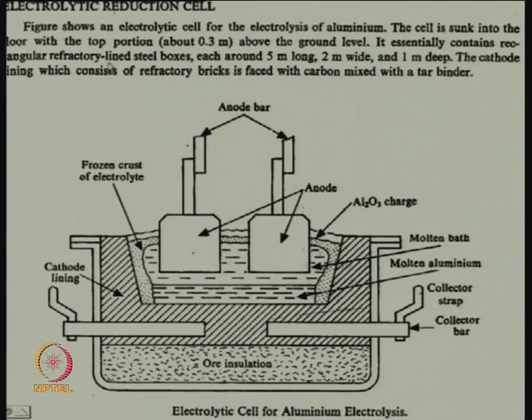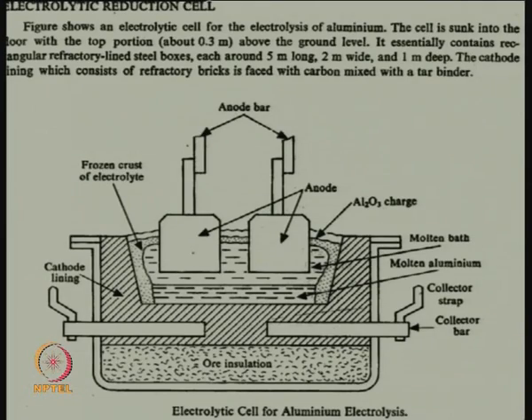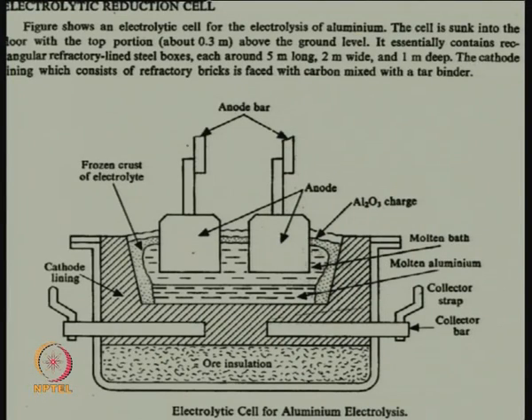The cell is sunk into the floor with the top portion about 0.3 meter above the ground level. It essentially consists of rectangular refractory lined steel boxes, each around 5 meter long, 2 meter wide, 1 meter deep. They are not very deep. Remember, I have always said that for electrodes you cannot go for depth. Sorry, there is a correction here. There is no question of a cathode which is hanging vertically. Here the cathode is a horizontal cathode, and the cathode lining, which consists of refractory bricks, is faced with carbon mixed with tar binder. So, this is the basic scheme.